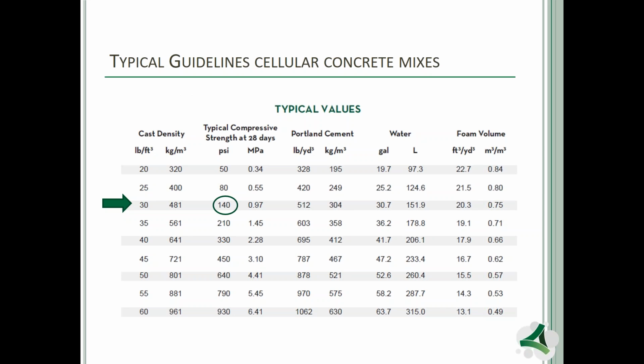So traditionally compacted backfill being what, maybe 110, 120 pounds per cubic foot, versus the cellular concrete at 30 pounds per cubic foot, giving a higher compressive strength than we normally would get from traditionally compacted backfill. A 30 pound per cubic foot scenario will give you about 75% air structure within the material. And that's what makes it lightweight.